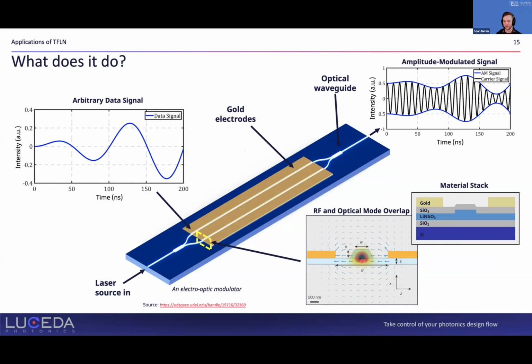The fact that there is an electrical field present across the lithium niobate material slows down or speeds up the light in that material. So it adjusts the optical index. And by doing that, we can speed up one arm of our device and slow down the other arm. And then when our light gets to this combiner at the end, it will either be constructive or destructive interference, and we get our modulation pattern.